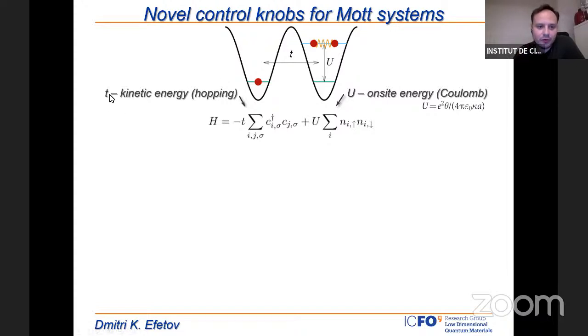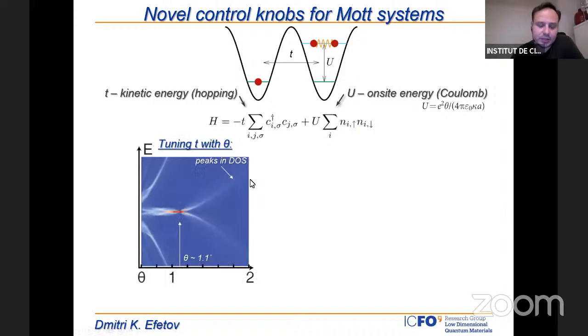So T, as I showed before, is the kinetic energy, which is just related to the bandwidth of the flat band. And the bandwidth of the flat band is a function of the twist angle. So we can slightly increase T by making the twist angle slightly larger than the magic angle. So we can actually tune T. This graph here shows the bandwidth, which is defined by the spacing between those density of states peaks. It is really tunable. A twist at the magic angle of 1.1 degrees gives a minimal bandwidth, but if you go slightly away from that angle, the bandwidth increases and therefore T increases.